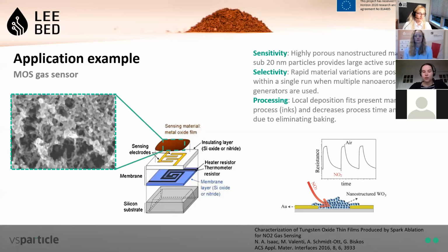And then the observed sensitivity was 100 when exposed to 1 ppm of nitrogen dioxide in air at 200 degrees Celsius, which is really good, and it provides a considerable margin to go to even lower concentrations and be also able to sense these. And these films show a stable, repeatable pattern.